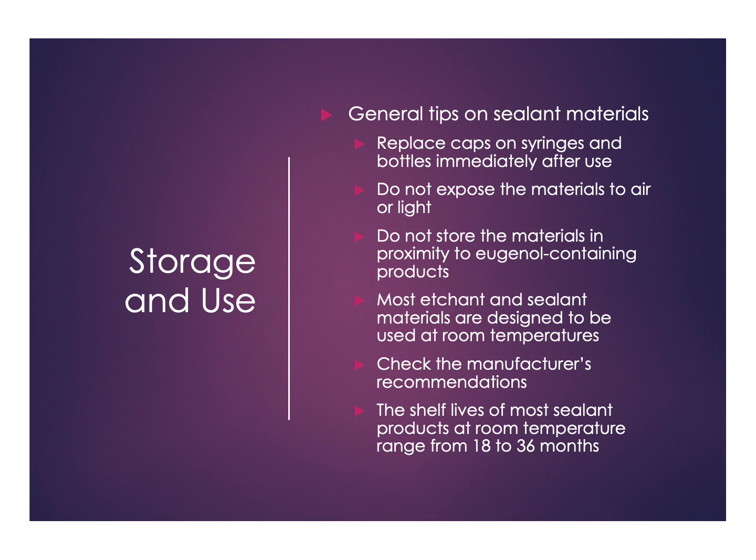Sealant material should be stored and used according to the manufacturer's instructions. Make sure you replace caps on syringes and bottles immediately after use. Do not expose the materials to light or air. Do not store the materials in proximity to eugenol-containing products. And store at room temperature. Most etchants and sealants are designed to be used at room temperature. The shelf life of most sealant products at room temperature range from 18 to 36 months.